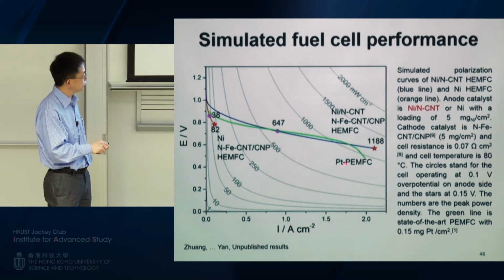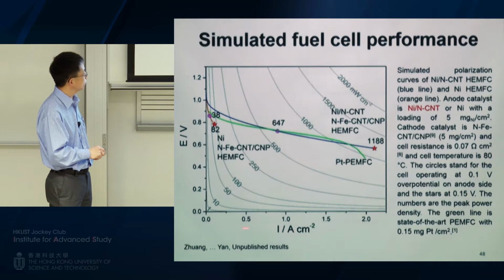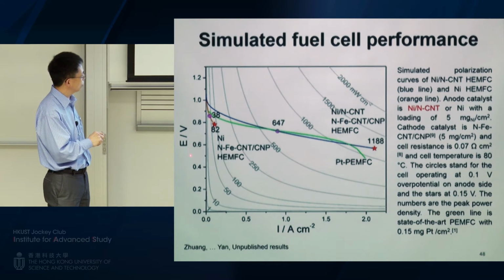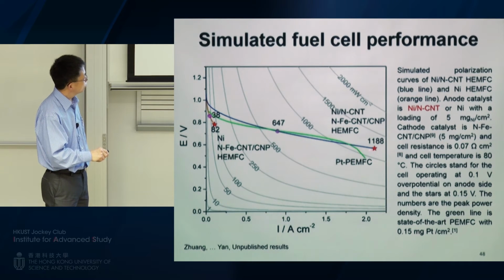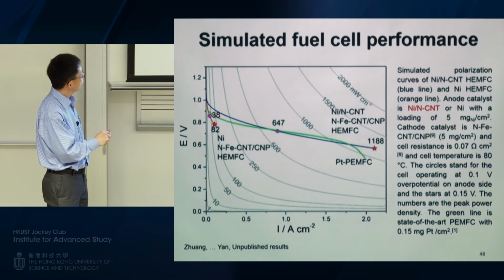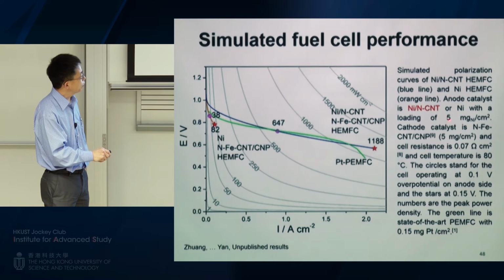This is the polarization curve. The horizontal axis is the current density. The vertical axis is the voltage. If you look at this blue curve, this is an experimental curve out of the 3M company. This is the highest performing PEM-FC, proton exchange membrane fuel cell. If you look at the green curve, this is our simulated polarization curve based on an experimentally demonstrated non-precious metal oxygen reduction catalyst and our nickel supported on nitrogen-doped carbon nanotube.